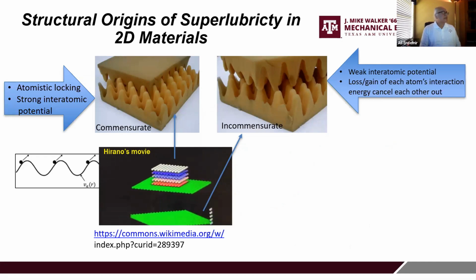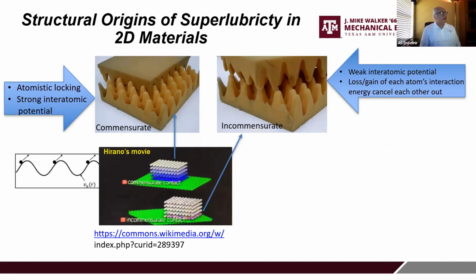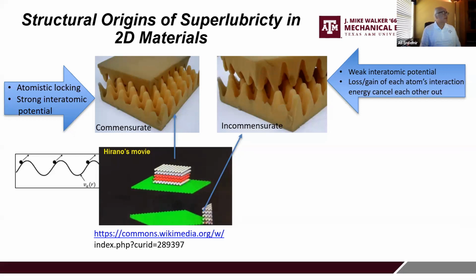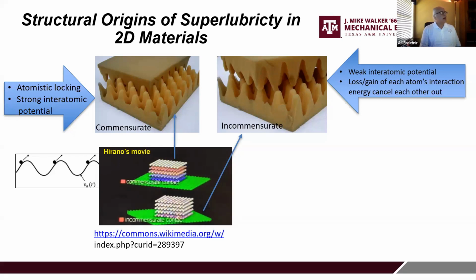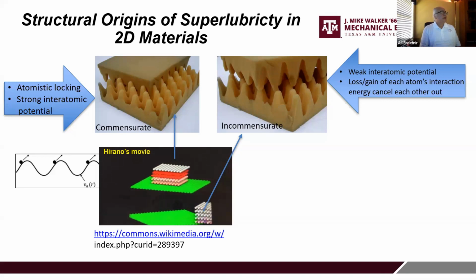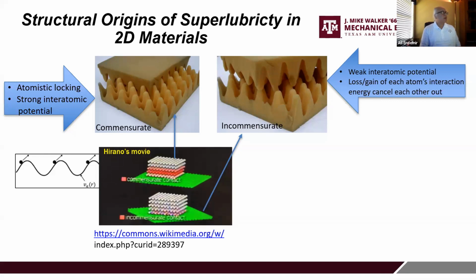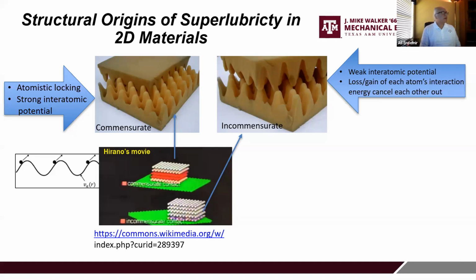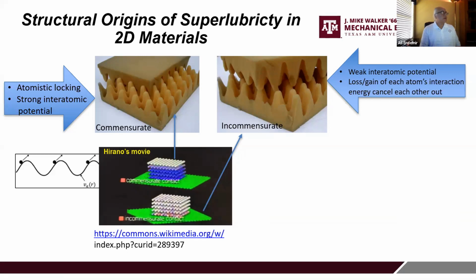These are described as, in the case of commensurate contact, you have two surfaces. They could be made out of the same material or similar, dissimilar materials, and their atoms on the surface are in full registry in the case of commensurate state of contact. And so, because of this full registry, you have atomic scale, strong atomic scale interactions, and thereby you have what they call atomic locking. And this will actually produce very huge interfacial adhesion, which will make these surfaces move with very difficulty.